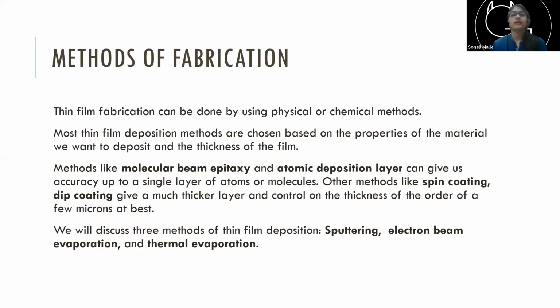Right. So there are physical methods and chemical methods for depositing thin films. Based on the thickness that you want and also the material you're depositing, there are a lot of methods you can choose from. If you want very high precision of the thickness, say up to single layers of atoms, say you want to deposit only two layers of atoms one on top of the other, there are methods like molecular beam epitaxy and atomic layer deposition. If you don't want very good control of the thickness, but you also want a thick coating, say we deposit resists when we want to do electron beam lithography, in that case, you do spin coating.